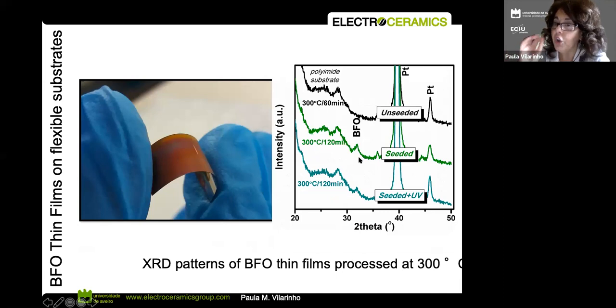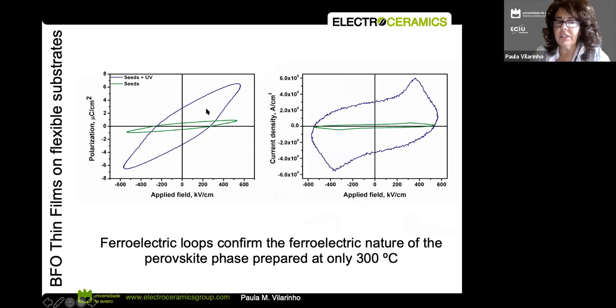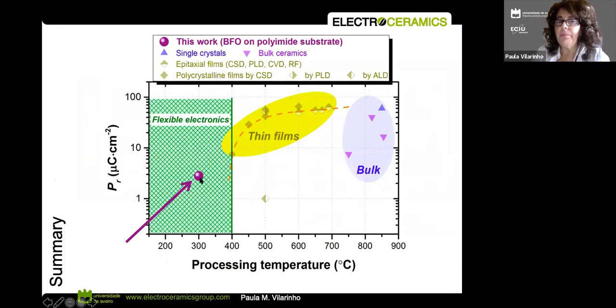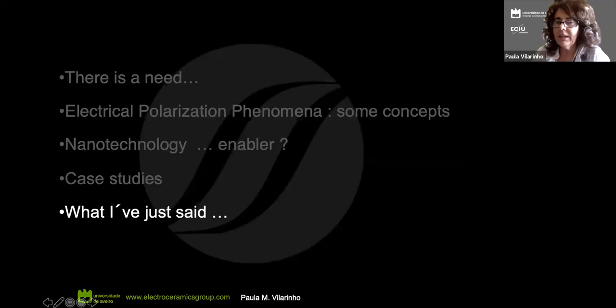So we already have an oxide. This is really relevant because this oxide is just formed at very high temperatures, around 600, 700, 750. And this is incompatible with polymer. So here is the answer. Here is the response of the materials that contain seeds and are treated just at 300, very, very low temperature, and we have a ferroelectric response. So I think this is a very nice result that really allows us to put here our bismuth ferrite deposit on polyimide substrates with a very low temperature of crystallization, making them flexible.